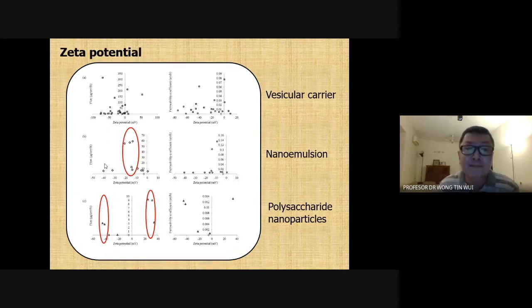Likewise for zeta potential. Now, it is known that the positively charged or negatively charged nanoparticle can actually promote skin drug delivery. Now, positively charged nanoparticles tend to attract to the anionic lipids of the skin, hence facilitate their penetration into the skin. Now, negatively charged nanoparticles tend to repel with the anionic lipids of the skin, making the skin fluidized and softer, and the aqueous pore become larger, and this will facilitate the drug molecules that are released from the anionic nanoparticles into the deeper layers of the skin.